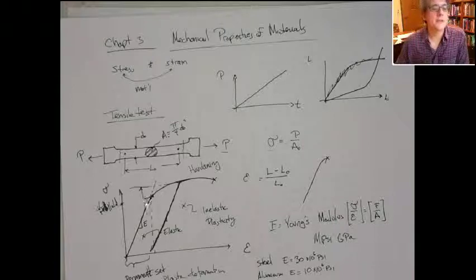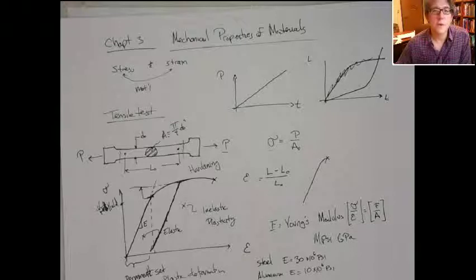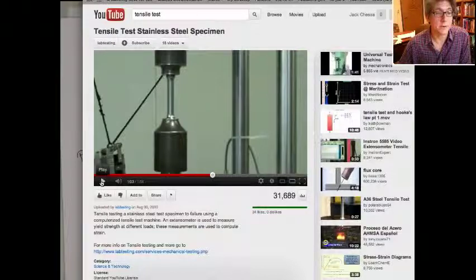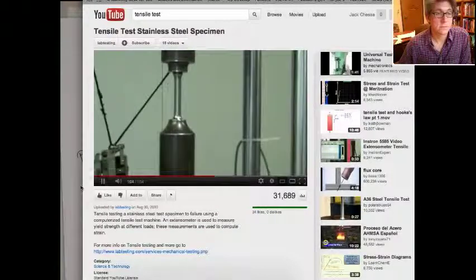They determine yield strength as the response starts to deviate from linear a little bit. Now you don't want to go too far with the extensometer on because it'll start to really deform and damage the extensometer. And that's what they're doing now. They've taken off the extensometer and continue to test to failure.